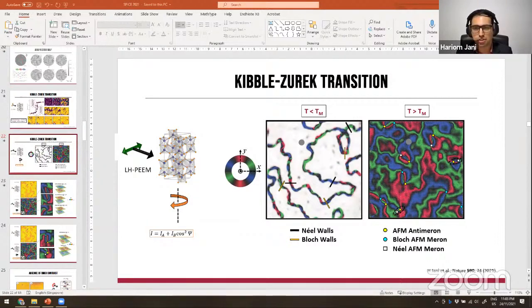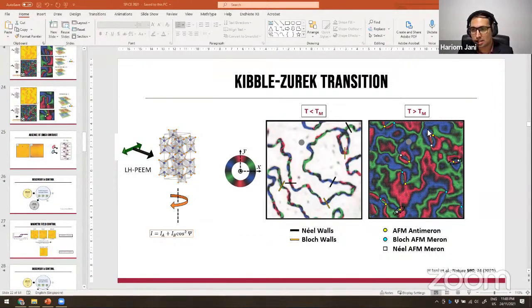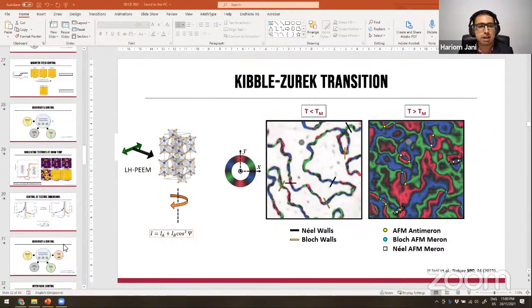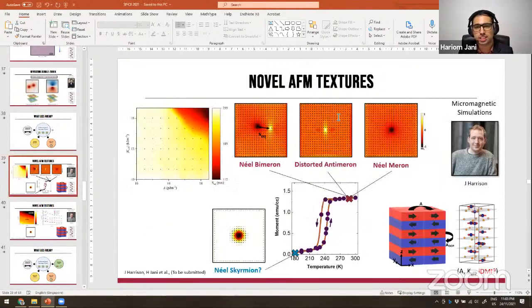Firstly, regarding the control of textures, one thing I would like to highlight is that if the system, as I have suggested here, contains sufficiently rich U1-like symmetry, it is possible to stabilize topological textures of charge half. That's first. Now, it is entirely true that the background of this is a mosaic of trivial domain wall structures, and this restricts the direct implementation of what I've shown you here, which is exactly the reason why I suggested the discussions in the later part of my talk, which show that we are able to create textures both in the in-plane state as well as in the out-of-plane state in a controlled manner once we have IDMI.